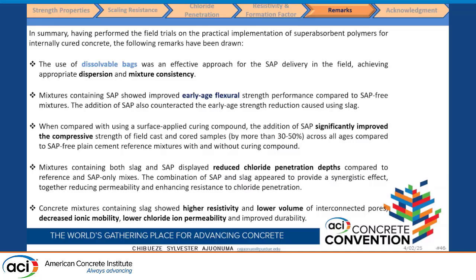And then also, when compared with the application of surface curing compound, we found that SAP significantly improved the compressive strength, from both the field cast and the cores, across all ages. And we also found that the mixtures containing both SAP and slag displayed reduced chloride penetration depth when compared with the SAP-only mixes. So this shows a synergistic effect together, which helps to reduce the permeability and enhance the resistance to chloride penetration. Finally, we found that concrete mixes containing slag show higher resistivity, as well as low chloride permeability.